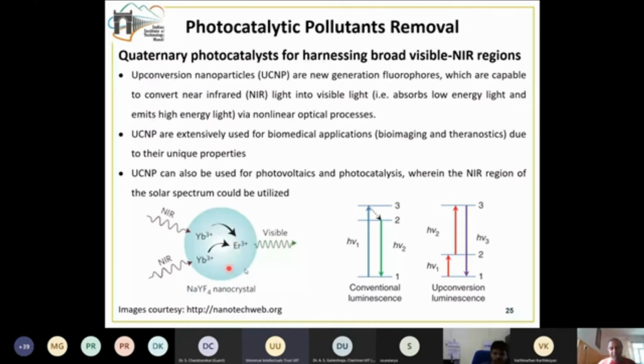This upconversion process can be contrasted with conventional luminescence. In conventional luminescence, there is an absorption from a lower energy level to a much higher energy level, then a non-radiative decay, followed by an emission from a slightly lower energy level to the lowest energy level. So the absorption energy is higher than the emission energy. On the other hand, in upconversion luminescence, multiple absorptions take place. One NIR photon gets absorbed here, another NIR photon gets absorbed here, and the emission happens from the higher energy level to the lowest energy level, which leads to a higher energy in the emission. So this is the upconversion process.